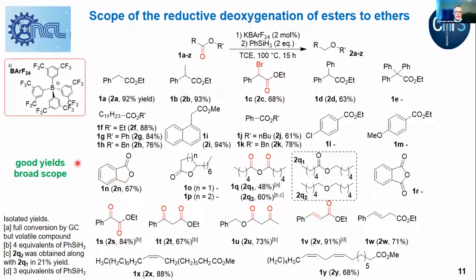Regarding lactones, arylated lactones were reactive and could be converted to the corresponding ethers. However, alkylated lactones were not reactive at all. By comparison, anhydrides could be reduced completely provided 4 equivalents of silane were used. However, phthalic anhydride was not reactive.